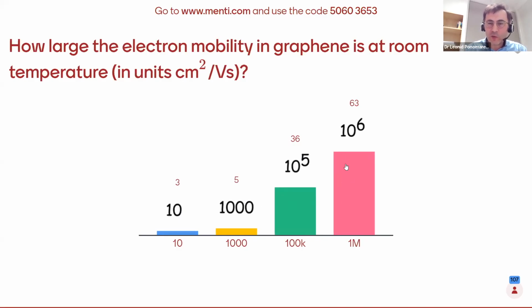This is because at room temperature, electrons are scattered mainly on vibrations of the crystal lattice, the thermally excited vibrations of the crystal lattice, and it's impossible in any semiconductor to make it 1 million at room temperature. We can do it at low temperatures, no problem. But at room temperature, we are limited by phonons.